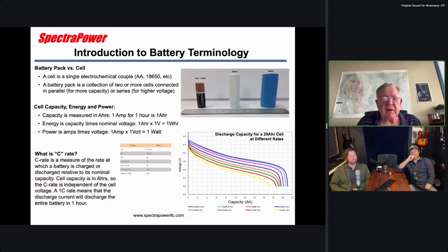But in an EV, you have a balance that you have to achieve where, when you accelerate away from the stop sign, you're going to be discharging at a high rate. And that can go up to like 3, 4 C. And then when you settle down into cruise, at 40 miles an hour or something, the rate's going to drop dramatically, and that will allow you to use the energy in the cell much better.